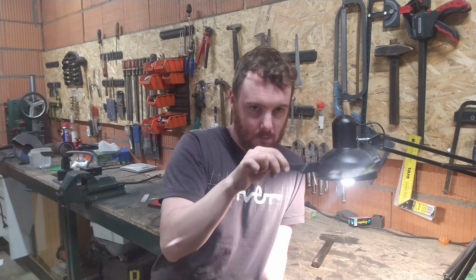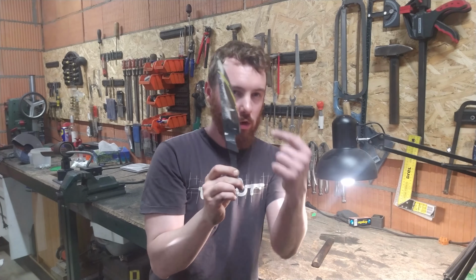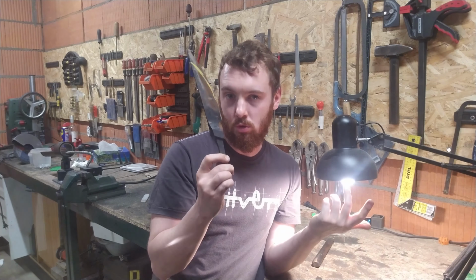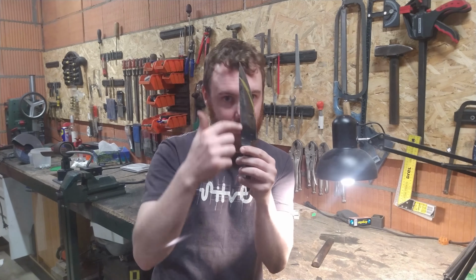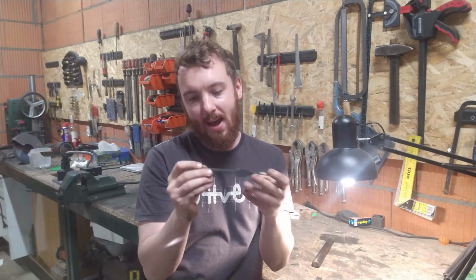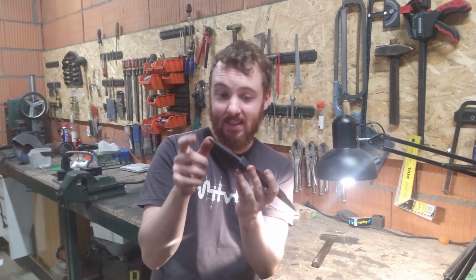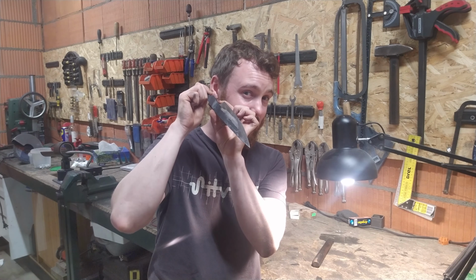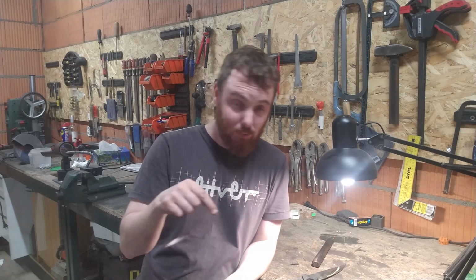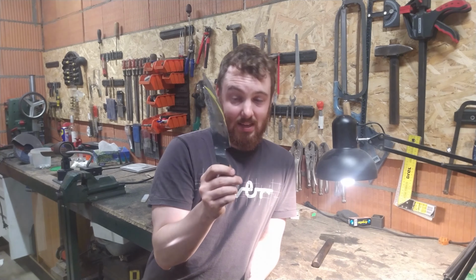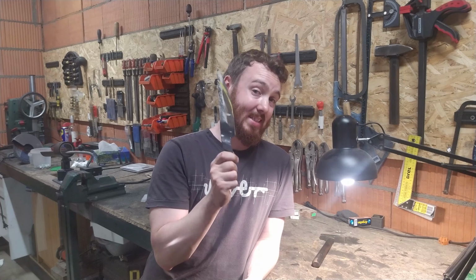In this case, it is something that makes the grain structure better. So actually what I think is, because I put the blade in the oven tip to the back wall, it just got overheated during the normalizing cycle and probably also during the soaking before the quench. So the tip is damaged and the heel is good. I should break the tongue to verify if the grain structure is okay, but I didn't heat treat it. I didn't quench the whole knife, I just quenched the blade, so I can verify it. But I'm going to cut the blade again, remove the crack, and I'm going to anneal it, normalize it, quench it, and we are going to test it again. But I will set the oven to a little lower temperature.